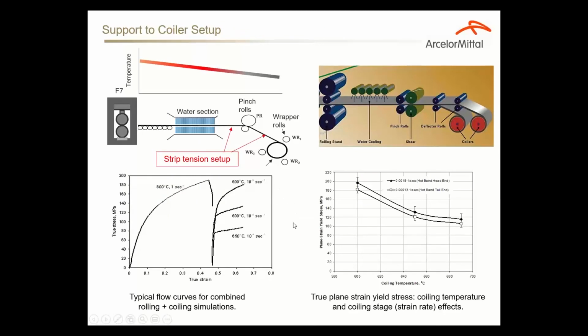We also use our Gleeble machine to assist the mills in setting up the tension on the runout table between the last stand and the coiler. There are two types of tension here. We do run tensile and compression simulations to determine the yield strengths in plane strain, tension, or compression. For tension, the information is fed into the coiler control system. For compression, it is necessary to know how to bend the strip around the mandrel and not to break it.